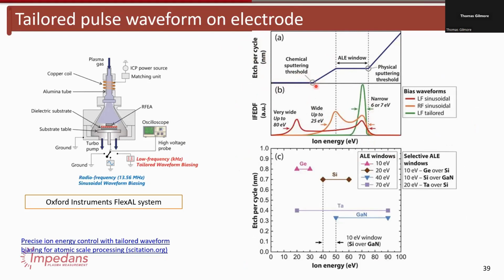There's some sort of threshold at which you start doing something. There's the atomic layer etching window where you have the self-limitation, and then you get to the point where you have physical sputtering. If you have a broad distribution, you could have parts of the distribution sitting in each of these windows. By going to a narrower distribution, you can sit comfortably in one of the windows at the rate that you want, as opposed to having contributions from multiple different windows. So this is why it's important for atomic layer processes going forward.